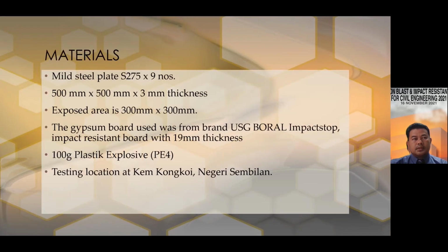Now, going to the methodology. The materials used are mild steel plates, S275, 9 pieces of it. The plate dimension is about 500 mm by 500 mm and 3 mm thickness. The exposed area is about 300 mm by 300 mm. For gypsum board, we use impact resistant board, which is 19 mm thickness from USG Boral, and each sample will be subjected to explosion from 100 grams of plastic explosive. The testing location is at Camp Congkoi, Negeri Sembilan, one of the UPNM facilities.